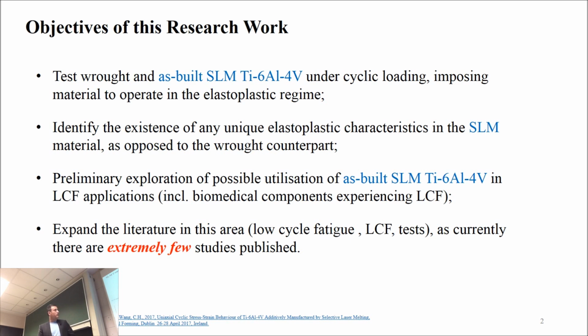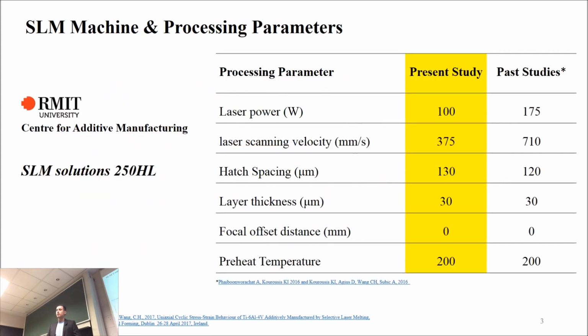What we did is we got some samples out of the SLM machine, and we tried to compare them with the typical behavior of wrought metal. First of all, we were trying to see some stuff around the microstructure. Of course, the objective of this research was not to identify the full microstructure characteristic of this material, rather to identify the macroscopic response under stress and strain.